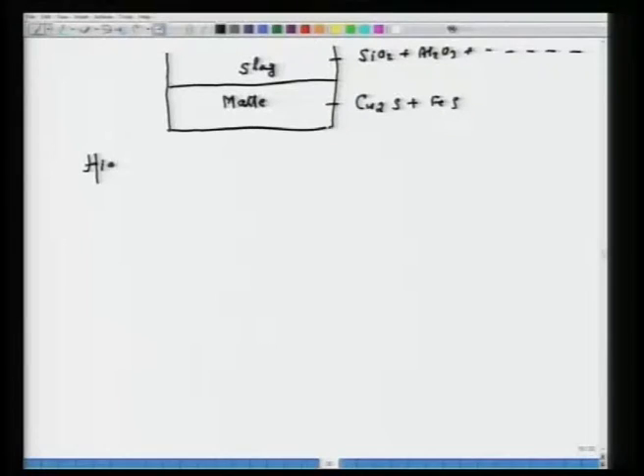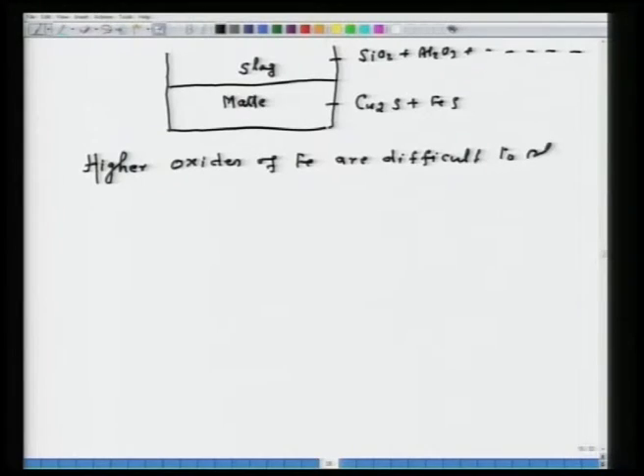Now, it should also be remembered that higher oxides of iron are in general difficult to slag, meaning difficult to remove. This precaution must be taken during roasting. During roasting, you have to see that the iron is not converted to Fe2O3 or Fe3O4. It will cause a lot of problems in the smelting and further stages. So, therefore, a controlled amount of roasting is needed. Well, that is what you should know.